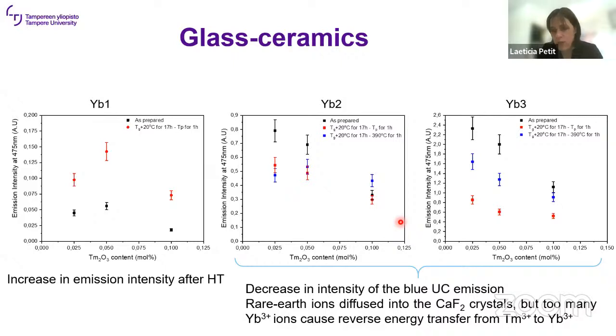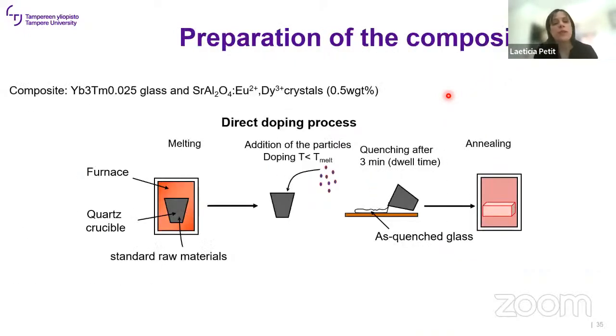So even if we have the rare earth going inside the calcium fluoride, we probably have too many ytterbium ions, and this leads to reverse energy transfer from thulium to ytterbium, leading to a decrease in the intensity of the blue upconversion. Nonetheless, if we compare the intensity of the three glasses, the glass prepared with 3 mol% of ytterbium and 0.025, 0.05 mol% of thulium has high intensity of the blue upconversion, and it's quite a promising material for optical battery.